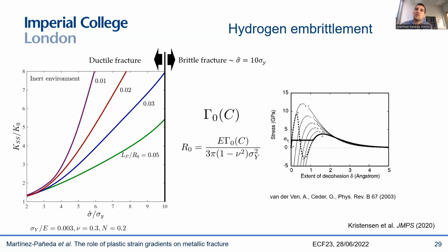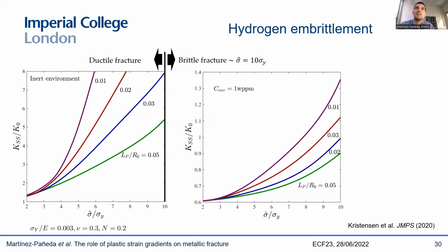However, the moment we bring hydrogen into the picture, what we know from atomistic calculations and from experiments is that hydrogen is going to reduce the fracture energy. The surface energy, the fracture energy, can be reduced by up to 40%, 50%, depending on the material, due to the presence of hydrogen atoms. So when we take that into account, this is going to change R naught, and therefore this ratio. For a given strain gradient plasticity length scale, we see that suddenly all these curves shift. And now, due to the presence of hydrogen, we're going to be able to predict brittle failure even if we consider cohesive strengths on the order of the theoretical lattice strength or the grain boundary strength.